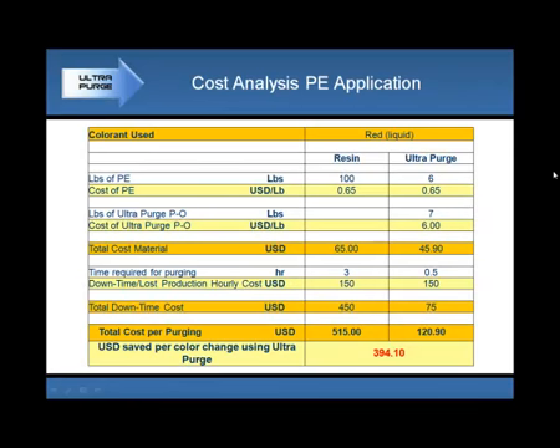Now, this is a very simplistic cost analysis of a closure application on a machine running polyethylene. Basically, it is a comparison between running just resin versus running the UltraPurge. As you can see here, with just resin, they used about 100 pounds of resin, and it cost about $65, and it took about 3 hours to complete the color change. At $150 per hour, they had a total downtime cost of around $450. Now, if we sum the cost of the resin plus downtime, we have an overall cost of $515. Now, by using the UltraPurge, they use only 6 pounds of UltraPurge.